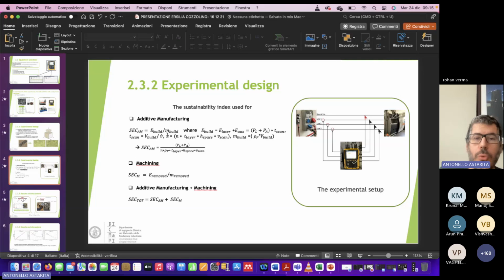So how to measure the specific energy consumed for additive manufacturing? The first important point is to measure the energy. So we use this device. This is just a power analyzer that we put between the machine and the socket in the wall. You have to be very careful in designing this kind of equipment, and also in designing the intermediate stuff that you put inside to be able to measure the energy required from the machine. This is a three-phase equipment, sorry, with the 3 lines and the neutral line. And this equipment allows you to measure the energy required during the process.